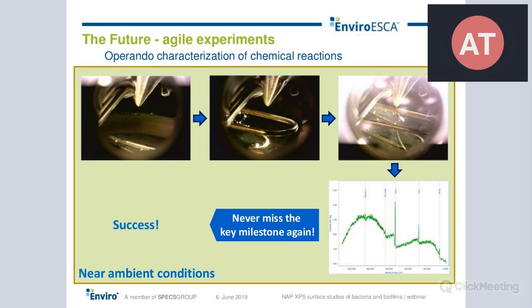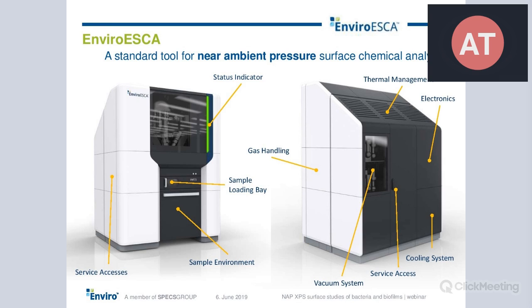And when you find this position, then you just etch it, you just wait, and while you wait, you always take the spectra. And this means that you are always taking spectra, means that you cannot miss the point where you stop to see the nickel and start to see the iron. And so this is a perfect method for operando studies, but as I said before, it is also a perfect method for other applications.